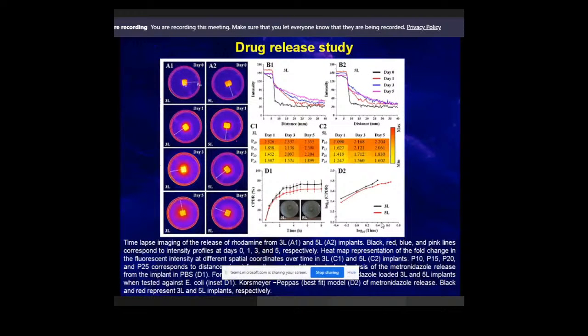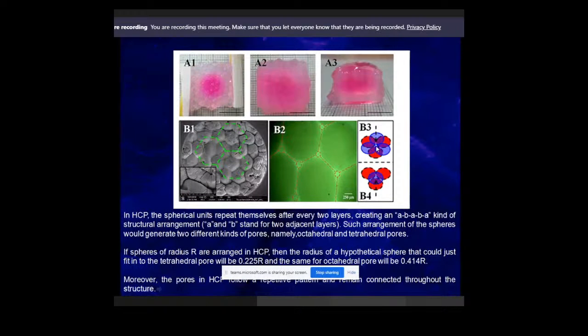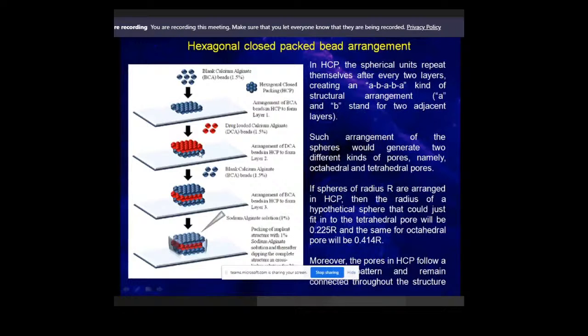Now what benefit will this kind of structure give? I would like to go back one more time. Here you see this is the pore. What is an important parameter for scaffold fabrication? These are the beads, and we are making it in a layer by layer fashion. My point is, if I can put any kind of bioactive agent at a particular location, I will have control over its spatial distribution. I can put multiple bioactive materials entrapped inside beads at different locations, and then create gradients of different growth factors or bioactive molecules inside the scaffold along with defined pores.